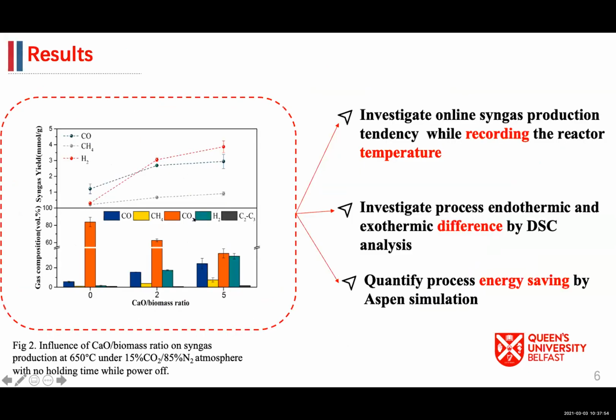From the offline GC results, basically we got a similar result to our previous work. With the increase of calcium oxide to biomass ratio, syngas yield increased. So in order to study this result further, we investigate from three perspectives. The first one is to investigate the online syngas production tendency while recording the reactor temperature. The second one is to investigate the process endothermic and exothermic difference by DSC analysis. And the last one is to quantify process energy saving by Aspen simulation.